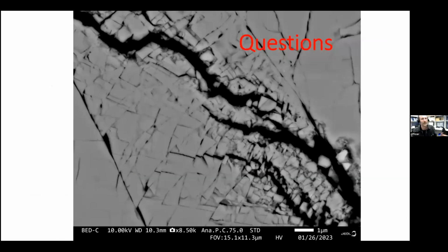So to conclude, basically, we are able to generate the high pressure phase. To generate fracture, we can see it within to the subfault scale, which is on the hundreds of microns. The focal mechanisms are all shear fractures, the same as deep focus earthquakes, and they appear to scale with deep focus earthquakes and other seismicity. And I didn't have time to talk about it, but here's what happens when you break something under 8 GPa. So this is some silicate data, which I left out of this talk, but I will take any questions.